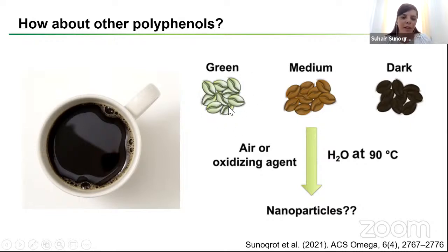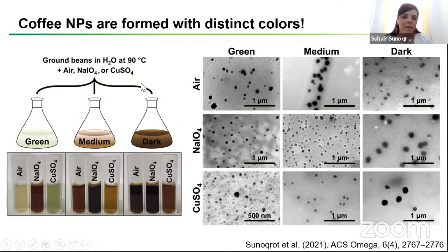We used the unroasted coffee beans, medium roasted, and dark roasted coffee beans. And we compared between each of them under the same conditions, but either without adding anything, just letting them stir in air, or adding sodium periodate as an oxidizing agent, or copper sulfate as another oxidizing agent. And as you can see from the images, we were able to obtain these different colored extracts.